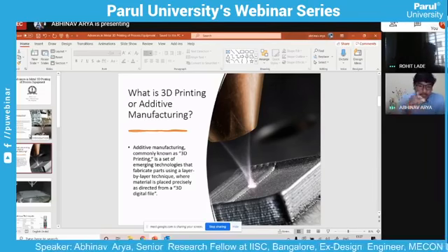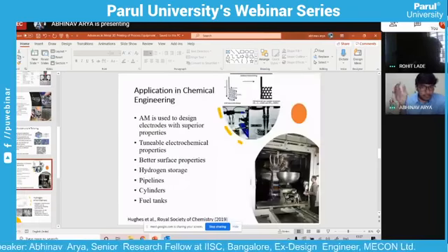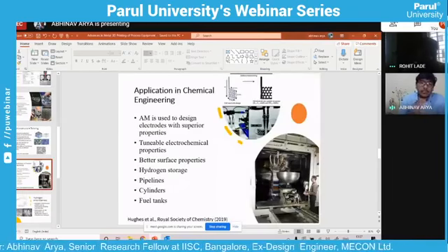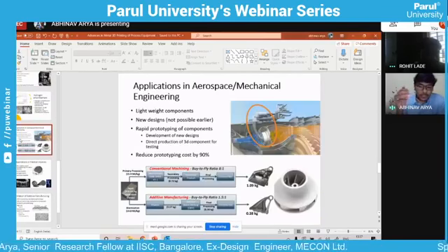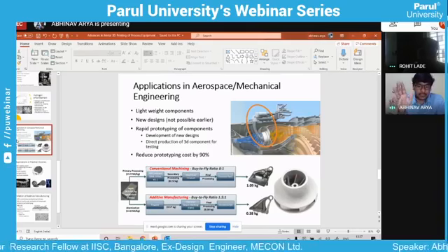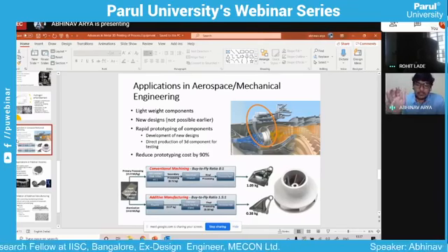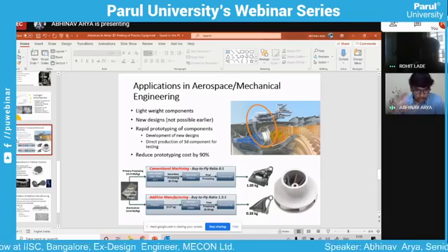Like I've shown in the aerospace industry, the fatigue resistance of these alloys is better. For the Ti-64 alloys produced by additive manufacturing, the fatigue resistance and the fracture toughness are better than the traditionally manufactured alloys.